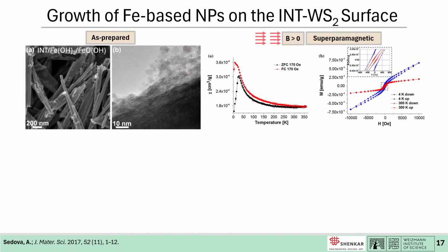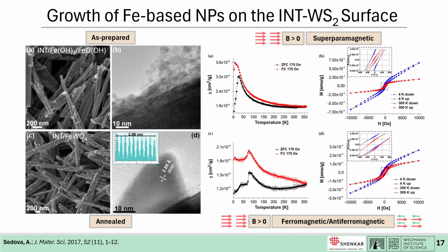Synthesis is based on the defects that the nanotubes have. So in the first step, I deposited iron hydroxide nanoparticles on those defects, and we could achieve a superparamagnetic response. And in the next step, I basically annealed the material, and we could achieve ferrous tungstenate nanoparticles that presented a competitive response of ferromagnetic and antiferromagnetic materials.